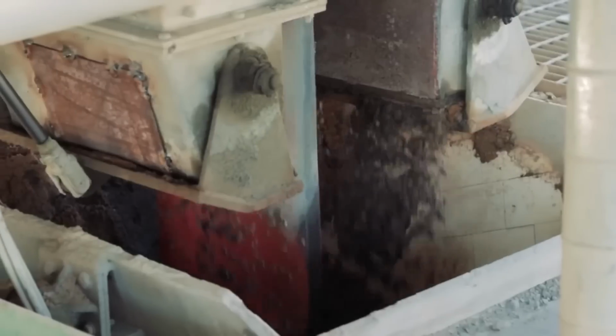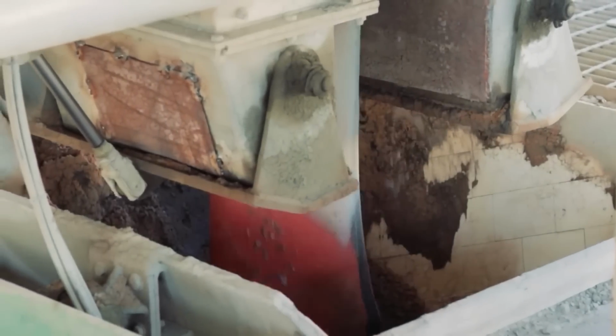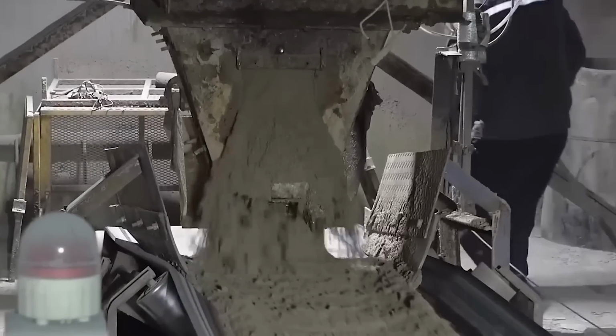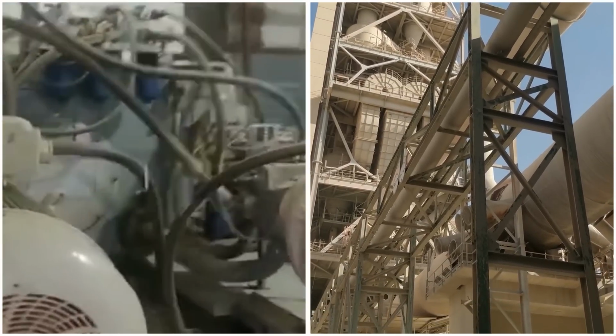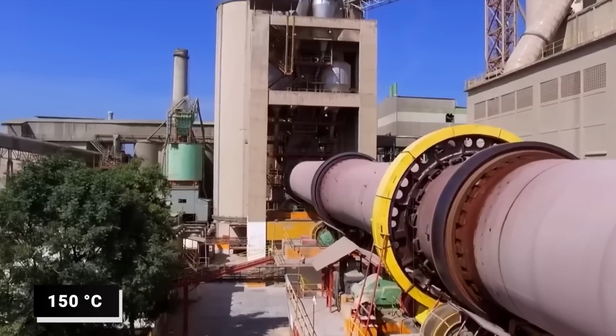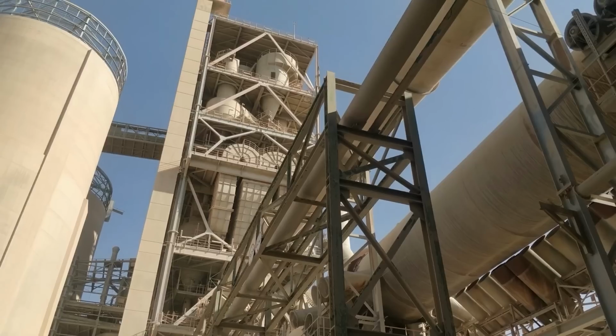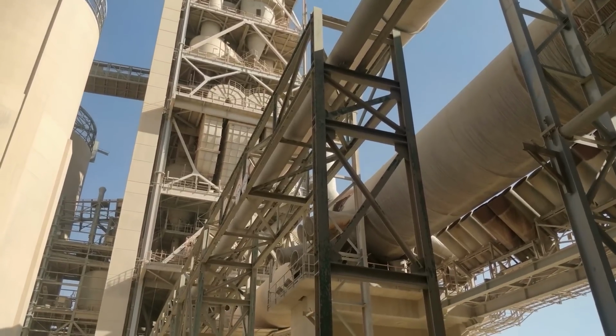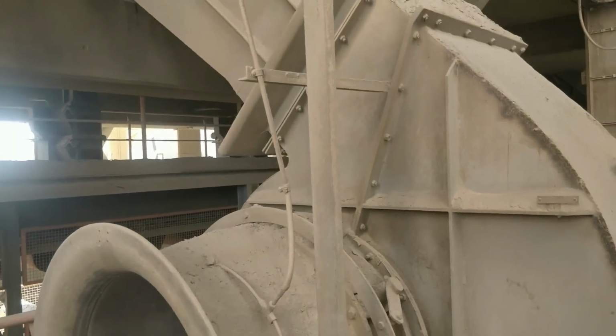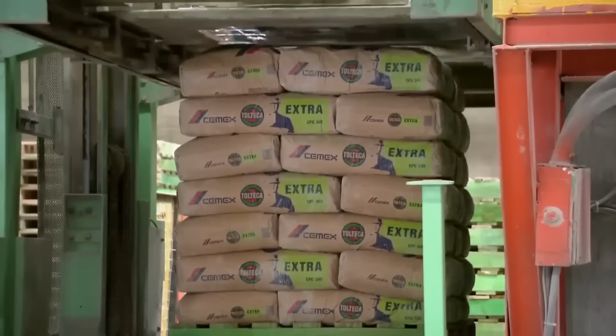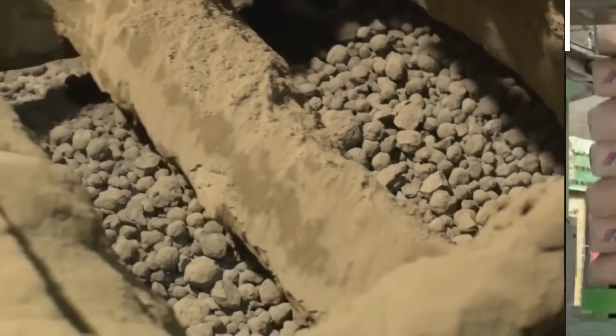degrees Celsius. Rapid cooling is essential to maintain the quality of the clinker and prevent unwanted reactions with moisture or other substances. The clinker cooler utilizes ambient air or preheated air from the kiln to bring the temperature of the clinker down to approximately 100 degrees Celsius to 150 degrees Celsius. The cooled clinker is then transported to clinker silos or hoppers directly by conveyors for storage and later for the cement grinding process. The hot air in the cooler is recirculated back to the rotary kiln for reuse, which further saves the energy consumption of the cement plant.